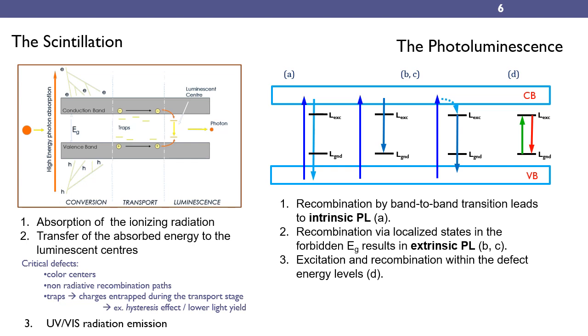By considering an inorganic material, in my case I will consider a wide bandgap material, photoluminescence and radioluminescence mechanisms can be, in simple words, differentiated because photoluminescence is based on an intracenter excitation, while radioluminescence is a three-step mechanism, and the radiative emission occurs only after a transport stage of the free carriers towards the emitting centers. Photoluminescence is affected mostly by the concentration of emitting centers. In turn, radioluminescence can be influenced also by other factors, like defects acting as traps, additional color centers, or non-radiative centers, especially during the transport stage.